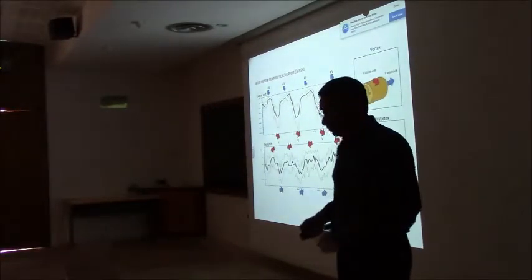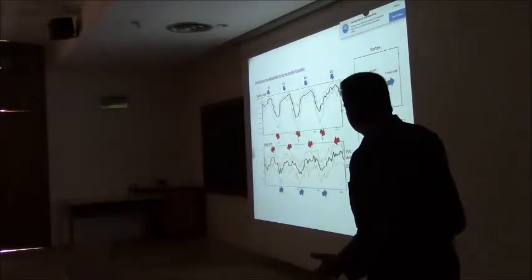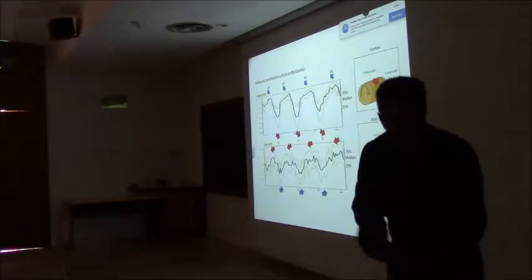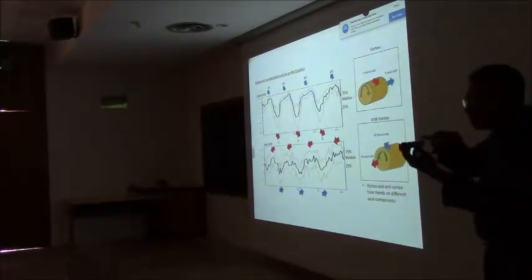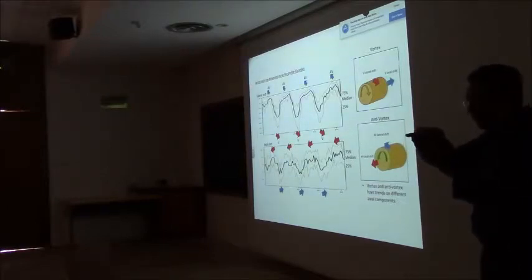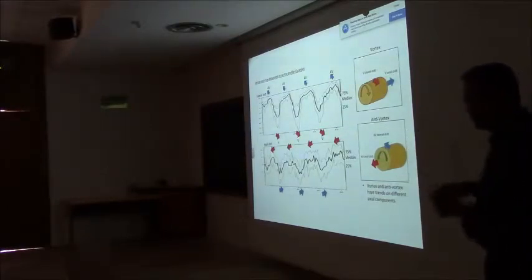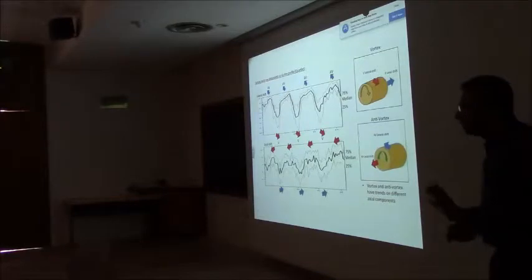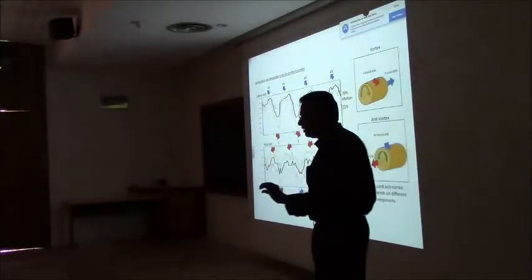In the x direction, xz plane, no problem. You see that in many different measurements. But we also see an axial shift, which is much smaller, typically about 10 to 15% of the lateral shift. Meaning, if this is my vortex, let's see if I can have a good analogy. Okay, this is good enough. There is a small component of the polarization this way, and of course there's a large component this way. And you can pick that up with this, it's about 10-15%. So we seem to believe now that there is a Y component which is measurable.